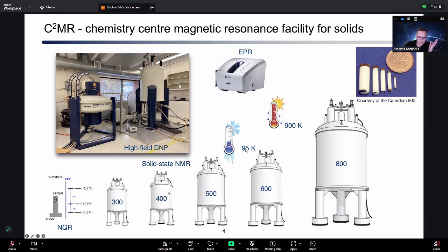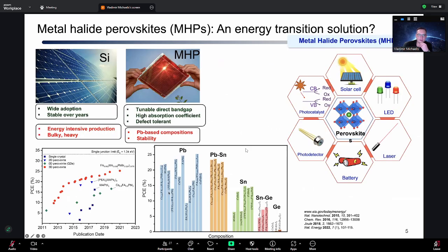Now, some of you may be fairly familiar with metal halide perovskites. Some of you may not. So I just thought I'd show this overview here of the interest and why we spend so much time on them. What has happened over the last 10 or 15 years is this relatively forgotten material, in particular methylammonium lead iodide, exhibits really nice semiconducting properties at the appropriate band gap, roughly 1.5 eV, where you can demonstrate that you can actually have solar energy conversion.